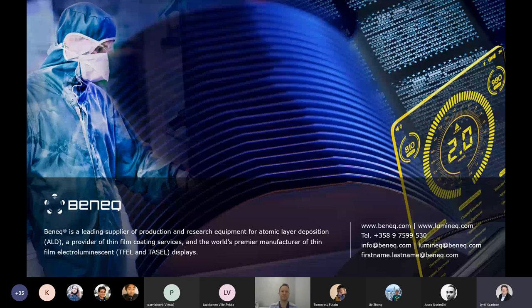Right. And then one more technical question. Does the hydrophobicity of the surface affect the deposition process during the deposition cycles? Because you used water also at one stage. Yes, it does. ALD can be used to coat materials like Teflon or gold and these kinds of things that are generally difficult to coat. But adhesion is not that great.